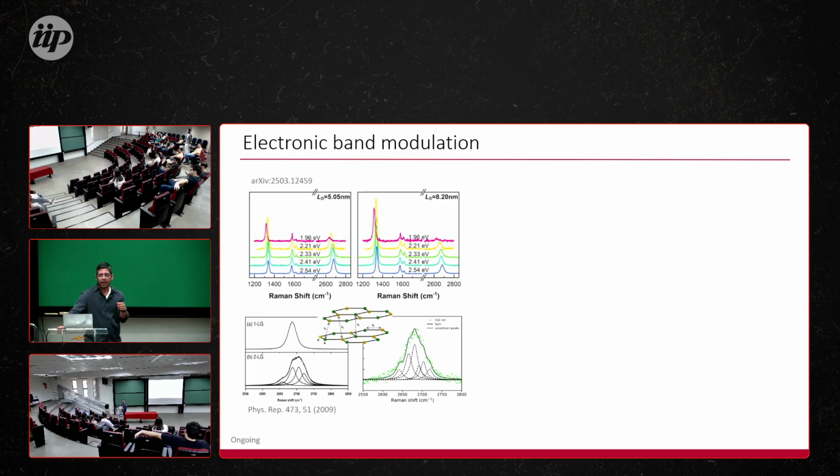Usually it's lower energy, but that will depend. So we observe in the Raman, right? Raman was actually a downshift, a redshift, and it should be a blue shift because of the vanadium introduction. So maybe even the lattice itself, because of the modulation of the electronic cloud, would be affected. So I'm not so sure if it would be higher or lower; it will depend on the kind of doping you're actually doing.